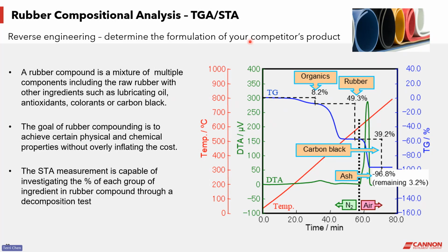The figure in this slide is a typical TGA decomposition spectrum of a rubber compound. The first 8% weight loss step here represents the decomposition of some small organic molecules or volatile stuff such as oil. The second weight loss step is the decomposition of the main rubber polymers. After the rubber decomposed, we switch the gas purge from using nitrogen to using air. Then the third weight loss step indicates the burning of carbon black. At the end of the test, any remaining residues are inorganic fillers.